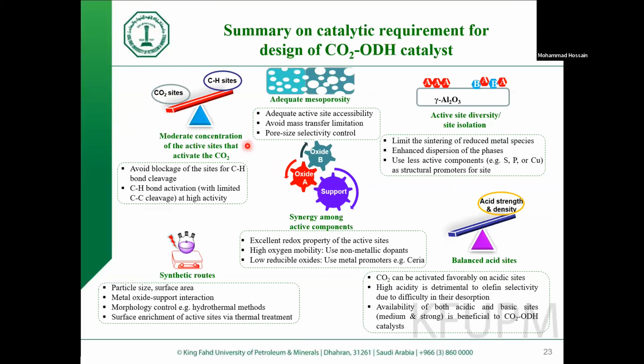Now, finally, we can summarize the whole strategy in terms of conversion of CO2 with light hydrocarbon to produce alkene. So first, one can consider the active sites. In terms of active sites, moderate concentrations are preferable to achieve good activity and to achieve the conversion of carbon-hydrogen bond and C-C bond cleavage. Adequate porosity is also important to offer adequate movement of the molecules, especially when you have higher hydrocarbon, and of course to minimize the mass limitation.